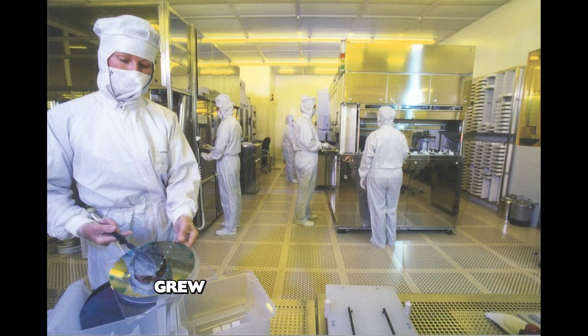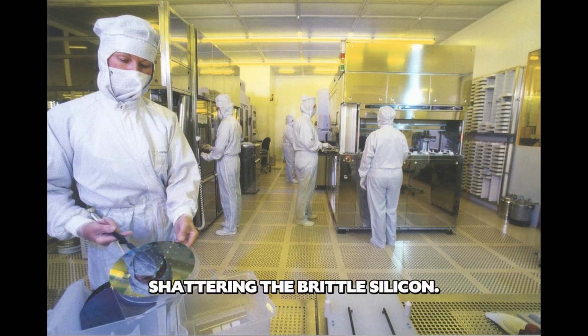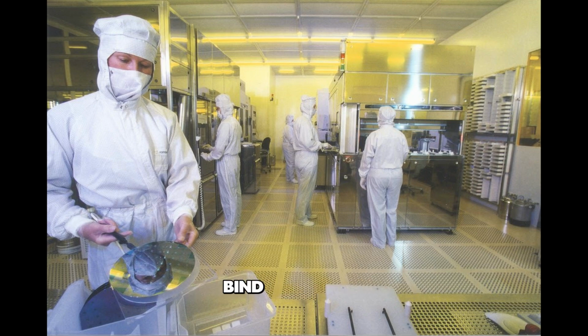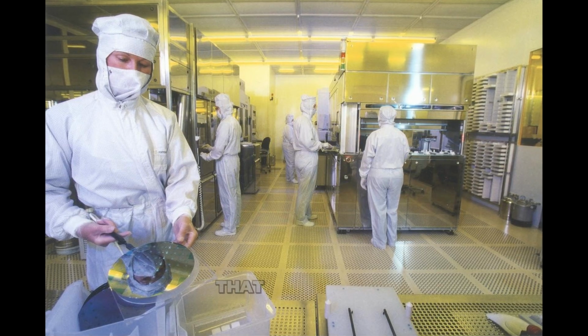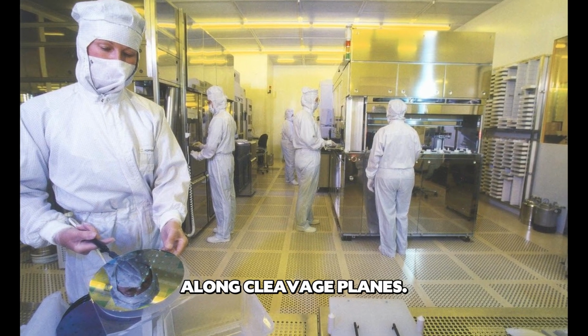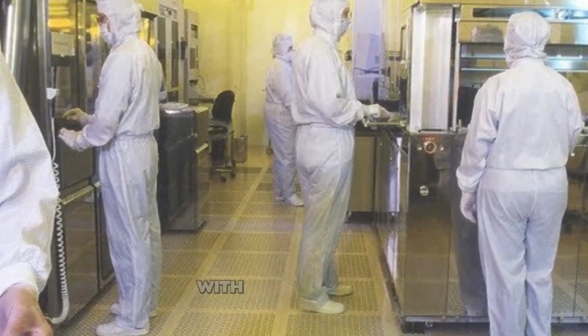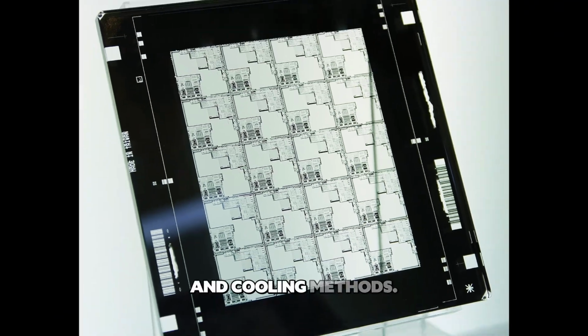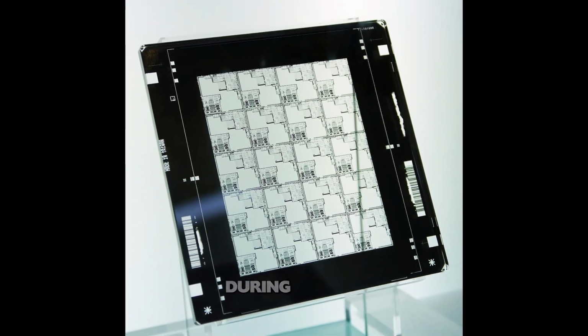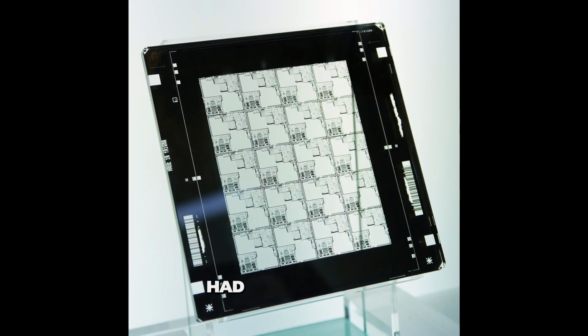When he successfully grew a crystal, perhaps 1 attempt in 5, the next challenge was sawing it into wafers without shattering the brittle silicon. Diamond-tipped saws would bind in the cut, generating heat that caused the crystal to crack along cleavage planes. Tannenbaum experimented with cutting speeds, blade thickness, and cooling methods. Most crystals broke during slicing. Those that survived had to be polished to optical flatness, with surface roughness measured in nanometers. A scratch invisible to the naked eye would create defects where transistors were fabricated.